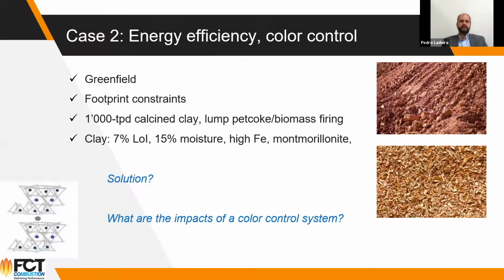And you start with a clay that's 7% LOI with 15% moisture, high iron, and montmorillonite. And what does it mean when you're talking about montmorillonite and low LOI? It means that you have this window of temperature between what is activation of clay and what is crystallization of clay, very narrow. So you have to have a very precise control of temperature. So the solution goes through a flash calciner.